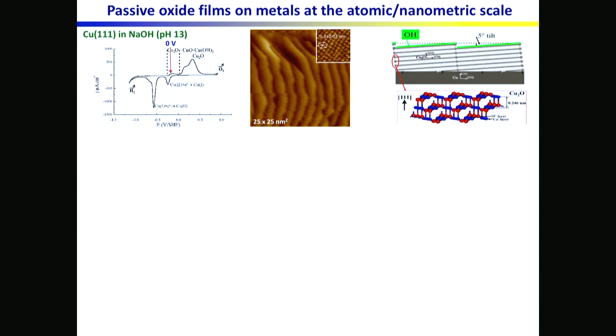We can of course use these to integrate the charge, and that would give one way to measure the thickness of the oxide. So what we were interested in was the growth of the oxide, and to do that we have been using extensively scanning tunneling microscopy in situ, so that is electrochemical scanning tunneling microscopy. We have seen nice examples in the presentation of Mark yesterday.